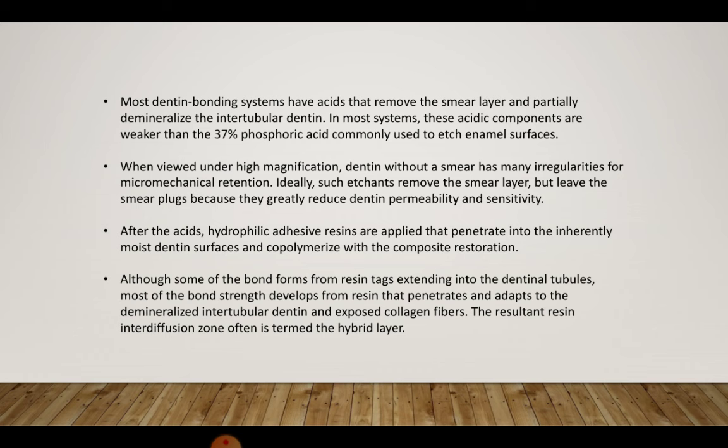So therefore, in order that such kind of dentinal sensitivity does not occur, we use acidic components which are weaker than 37% phosphoric acid to etch the dentine, so that just the smear layer is removed, leaving the smear plugs.